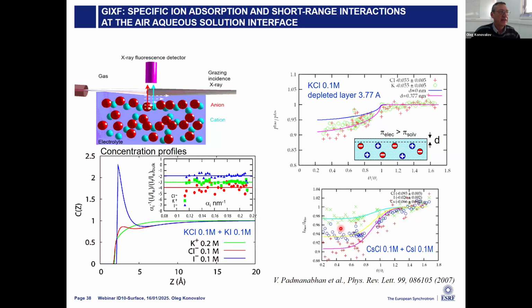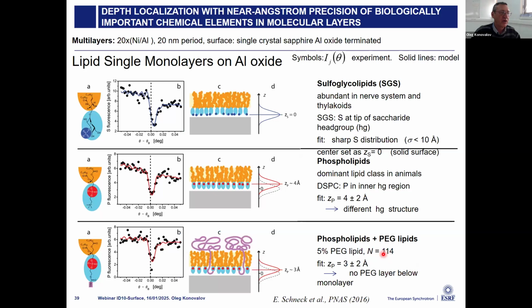So with the fluorescence technique, we can discriminate what is going on near the surface. And as I told, for example, here it was some mixture of different ions in the subphase, and we can see that they sit at different depths near the interface, how they arrange. Or for some monolayers or multilayers on a solid substrate, we can apply, in this case, standing waves. We can see how the system changes.